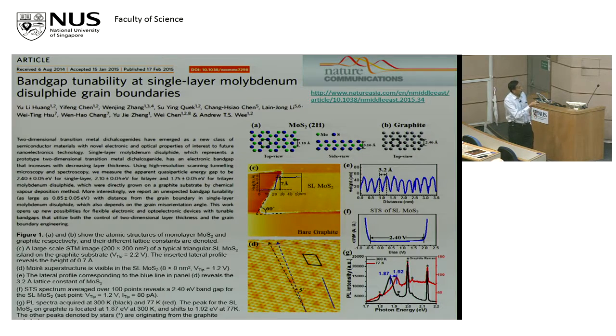So this is the atomic spacing, which confirms the material. We can even measure using spectroscopy, as I mentioned, in STM. We can measure the quasi-particle band gap. This is the electronic transport gap, 2.4, which is different from the optical gap because of what is known as exciton binding energy. So we can get its properties.